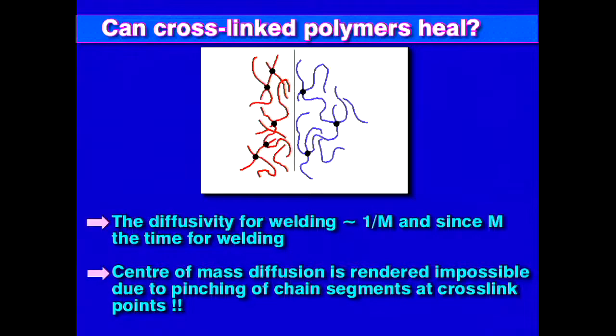But you know, there's a beauty there. The beauty is the two surfaces are healing. And how can gels heal? Because a gel is a macromolecule, a single giant macromolecule. If you take a film and you want to seal something, you heat it a bit, put the iron on, and why does that happen? One piece of polymer, another piece of polymer, you bring them together, put them over the glass transition temperature, and then there is reptation across the interface, and you have welding.